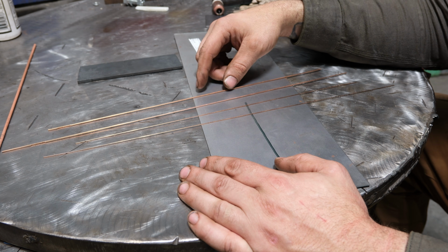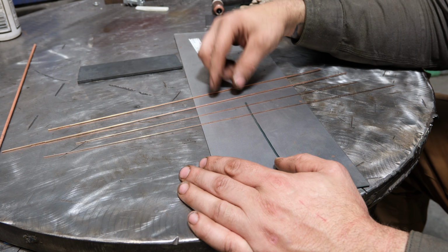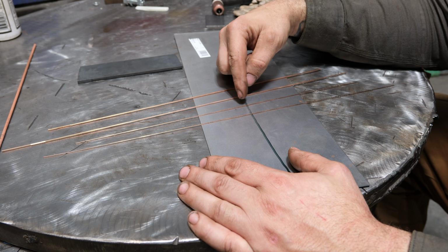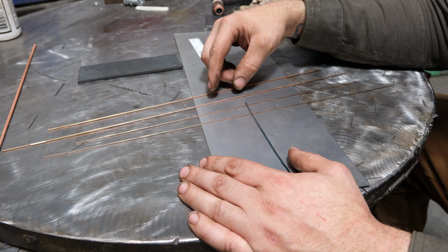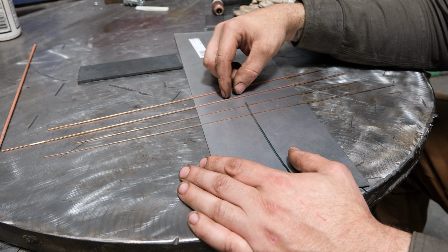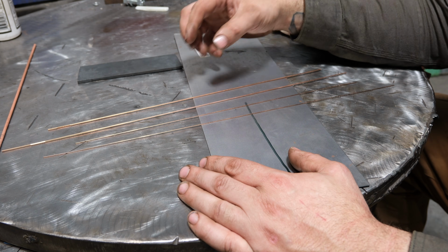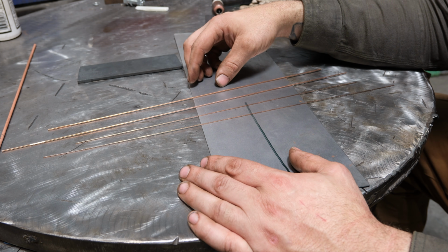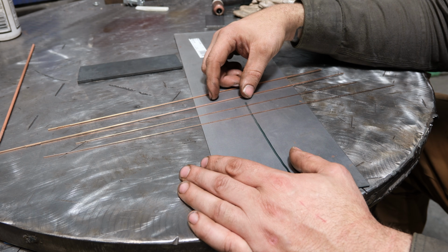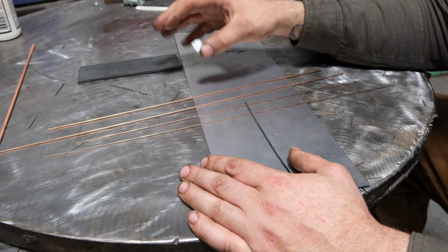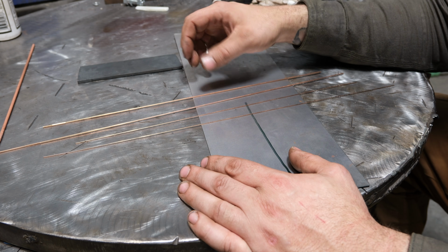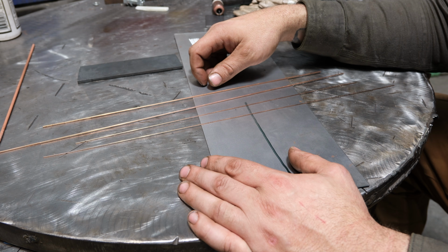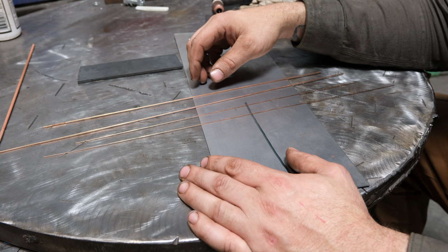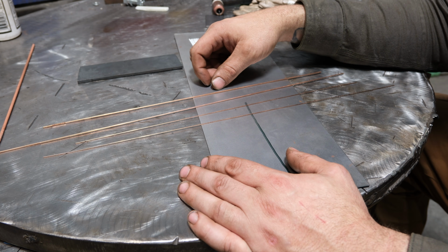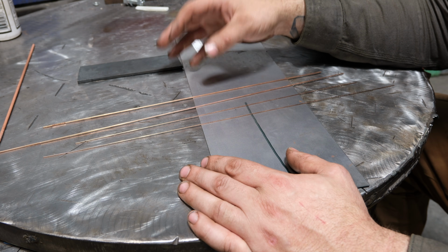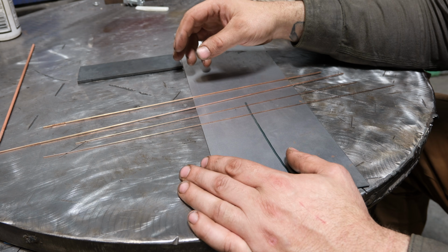The higher the skill you have, the more leeway you have in what rod you can use. If you find that when you're feeding the filler in, the molten pool more or less disappears or it humps up every time you try and dab, you're probably using too big of a filler or not enough amperage. So guess what? Increase the amperage, try again. If that doesn't work, downsize your filler rod. Like I said, the 1/16, as far as an amperage rating goes, probably about 40, 60 amps up to about 140, 150 amps. It works just fine. Above that or below that, you want to use bigger or smaller diameter fillers. Now keep in mind, guys, this is advice for steel, stainless, Inconel, titanium, all of those.